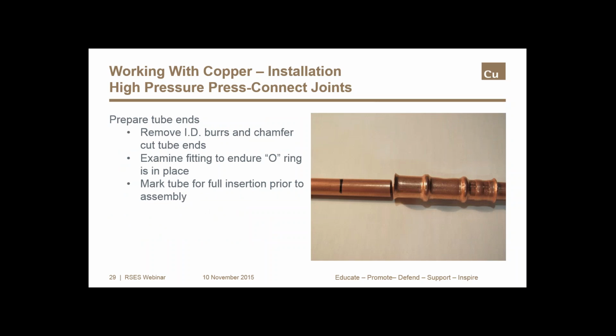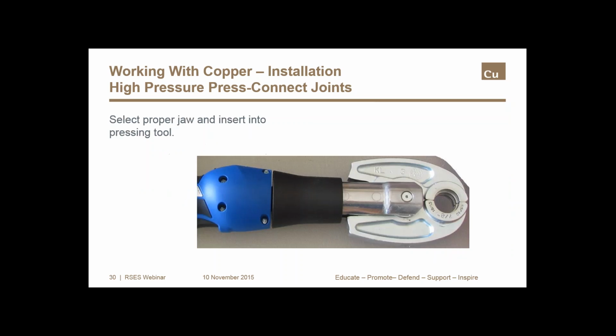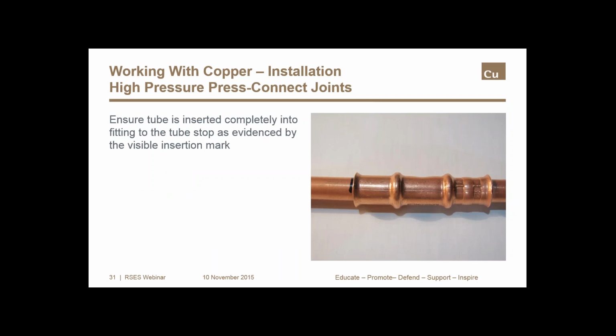As with any air conditioning or refrigeration system, cleanliness is important. The preparation procedure for press connect joints includes removing burrs and chamfering the cut end of the tubes. Make sure that the gasket is in place inside the fitting, and be sure to mark the insertion depth on the tube. Proper sized jaws must be used for the diameter of the tube that you're working with. The tube must be inserted completely into the fitting, and this is where the insertion mark on the tube will provide an easy check that the tube is, in fact, inserted completely.